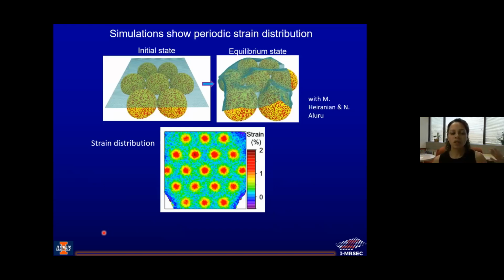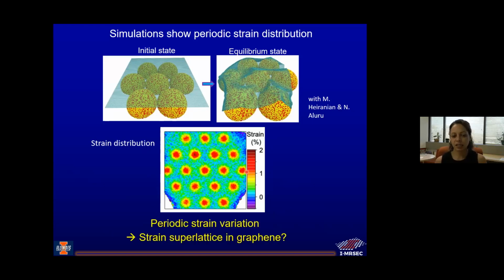But we really also want to look at the strain distribution. So these simulations indeed showed that we have this strain distribution across the graphene. So this plot here is a calculation showing that we get up to 2% or more strain at the peaks of each of these nanospheres across our entire graphene device. Okay, so that means that we have periodic strain variations, which leads us to one of our initial goals, which is creating a strain superlattice in graphene. Okay, so now I'll move on to experimental evidence we have of indeed measuring this sort of strain superlattice.